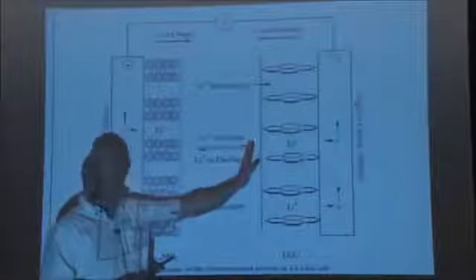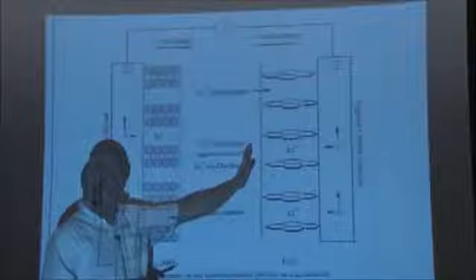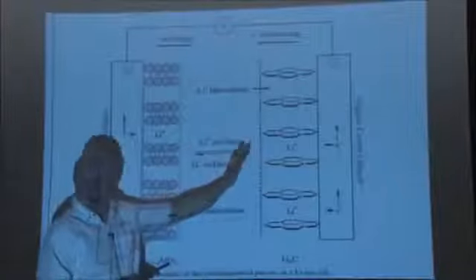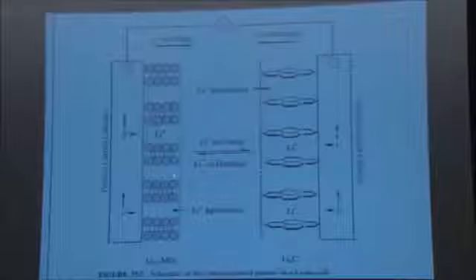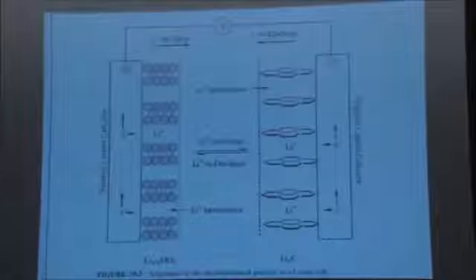But by luck and by chance, when the reaction occurs, the reaction products turn out to be solid on the negative electrode, and they form a passivating film that slows down and limits further reaction. And on the positive electrode, a similar thing happens. So by luck, these reactions don't destroy the battery. In fact, they form passivating surfaces that allow the thing to operate for many, many, many months.